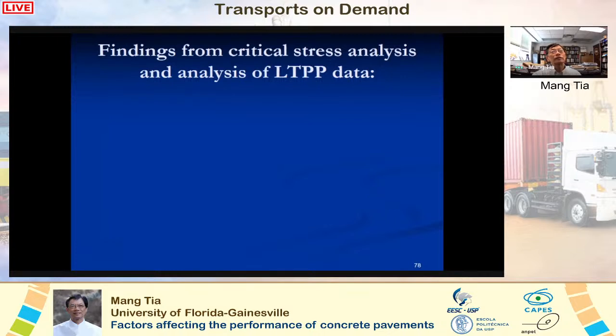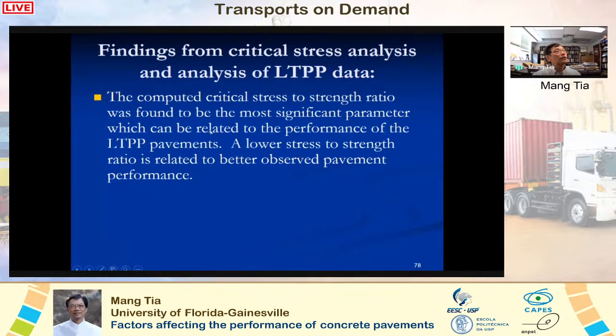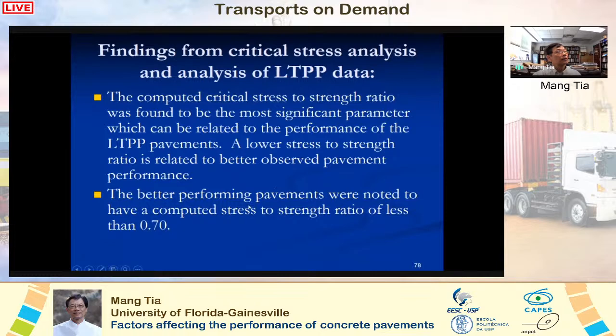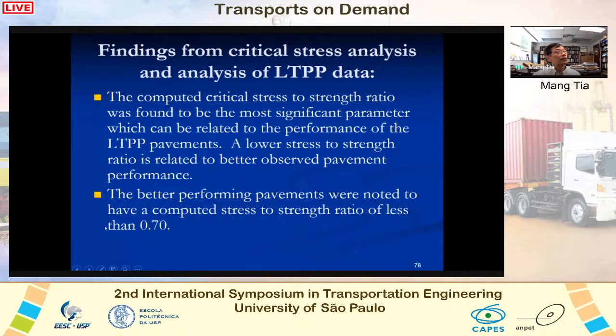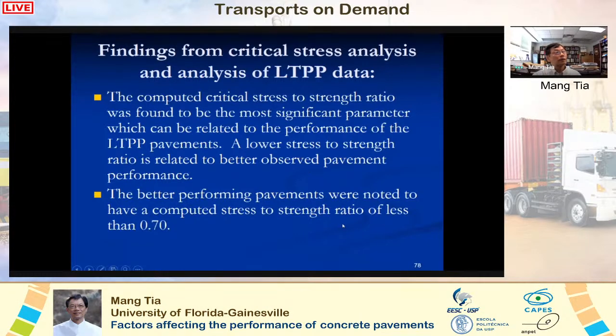Findings from the critical stress analysis are summarized as follows. The computed critical stress to strength ratio was found to be the most significant parameter which can be related to the performance of the LTPP pavements. A lower stress to strength ratio is related to better observed pavement performance. The better performing pavements were noted to have a computed stress to strength ratio of less than 0.7.